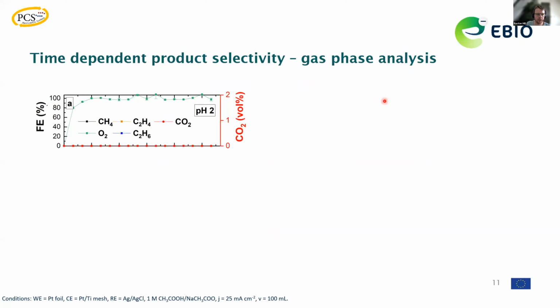And that's also what our time-dependent product gas phase analysis told us, that especially at low pHs, you basically form only selectively oxygen. And to give you a hint of what are the conditions that we're using here, we use the current density of 25 milliamps per square centimeter, which is rather low still, but we were just also limited by the conductivity of the electrolyte here.